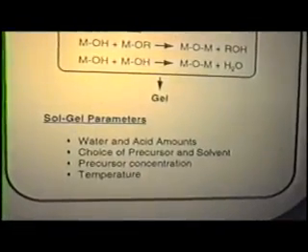In the sol-gel synthesis, there are various parameters which we can vary. By controlling these parameters, and I will look at two of them with you in a minute, we can control the properties of the gel. In this synthesis, we're going to end up with a gel encapsulating a solvent. The subsequent removal of the solvent results in either a xerogel or an aerogel.